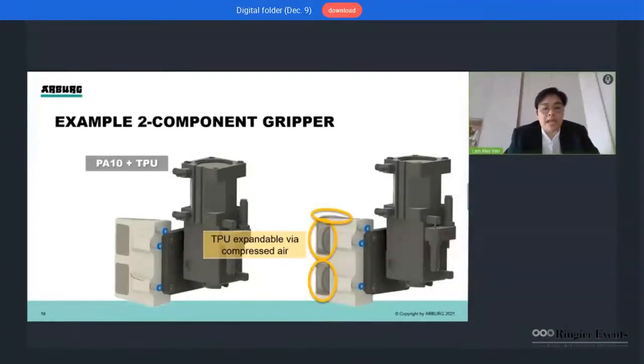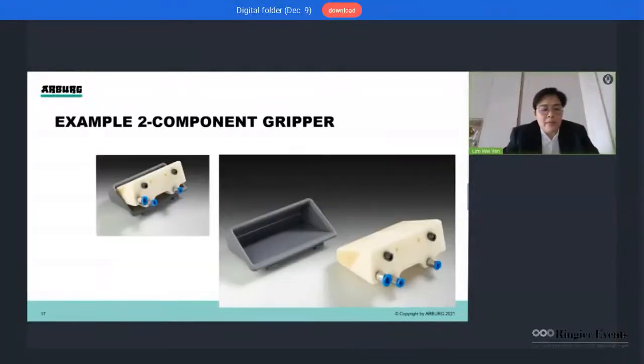The function of the gripper is enabled by compressed air again, and the hard polyamide housing retains the shape of the soft TPU membrane, which is really thin, about 0.6 millimeters. In this way, we were able to remove the handle from the mold gently without damaging the surface, something which is hard to achieve with traditional grippers or other AM technologies. Especially for this case, the TPU membrane has to have enough air tightness for the proper function of the gripper.